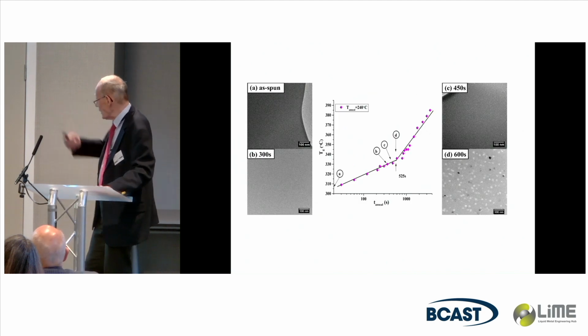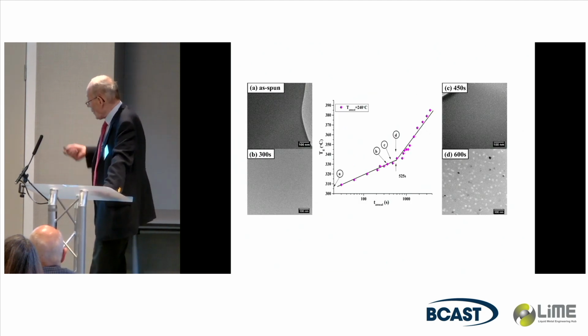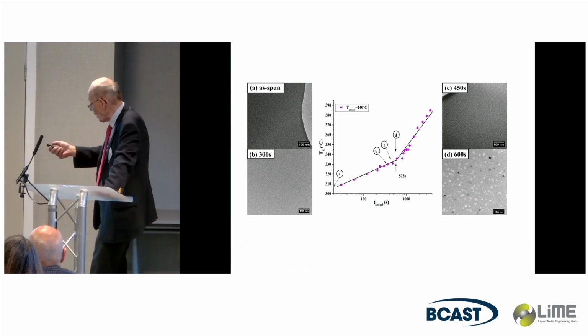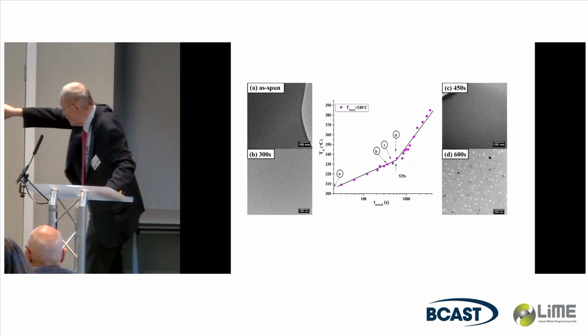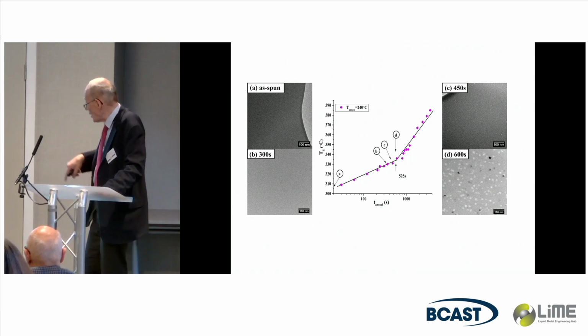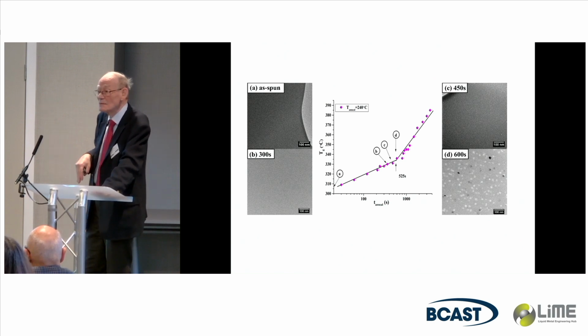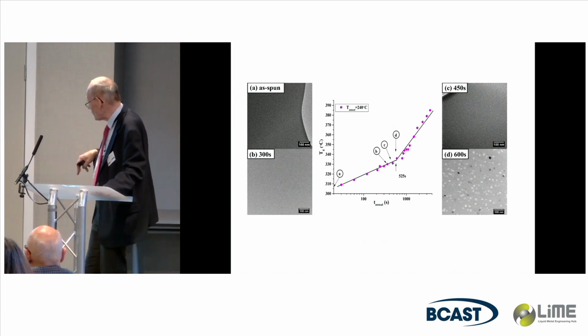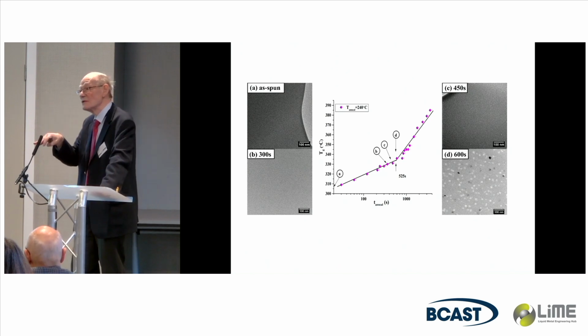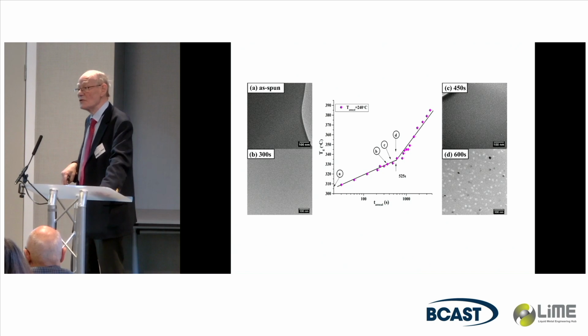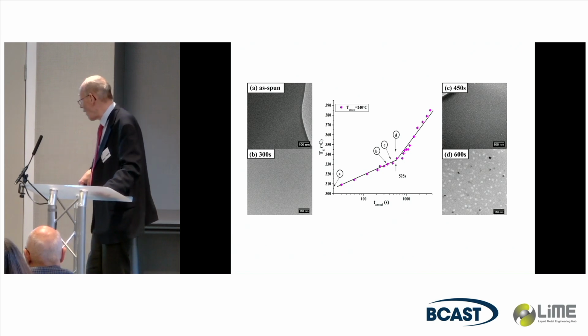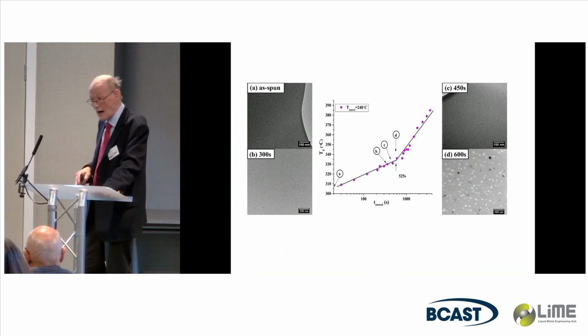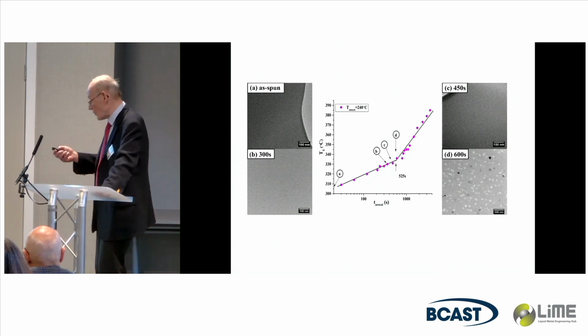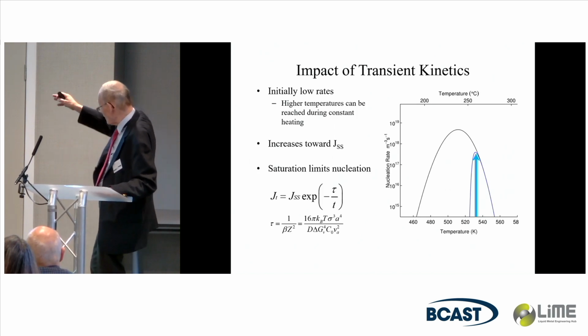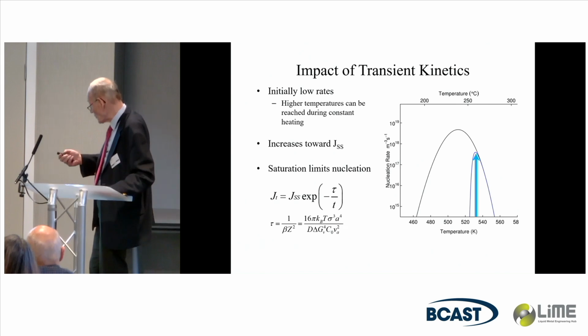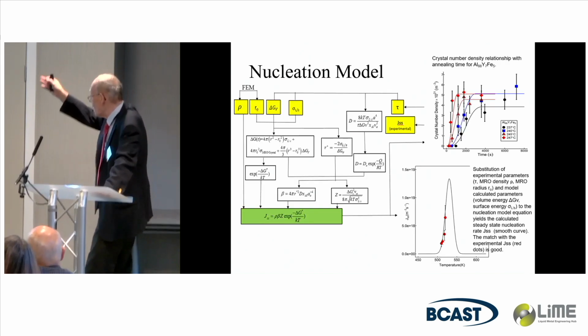And then when we anneal samples, we looked at them at different times. And measuring the glass transition, we have one slope that is associated with the structural relaxation in the glass. And then once the nanocrystal appears, the composition of the amorphous phase changes, and we get a different slope because the glass transition temperature changes with annealing. And so that break point is a very accurate measure of the delay time. So using that, we've shifted the curve to lower temperatures, and now we have very good agreement.